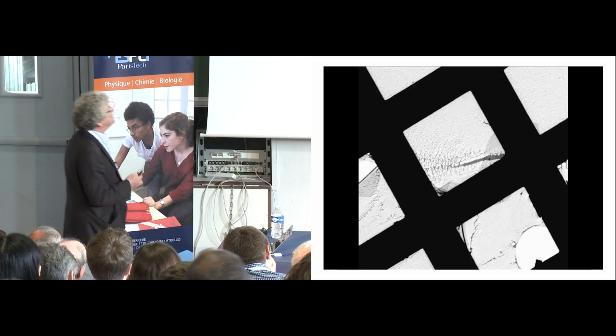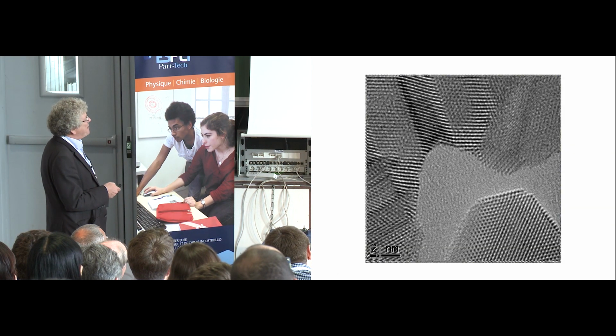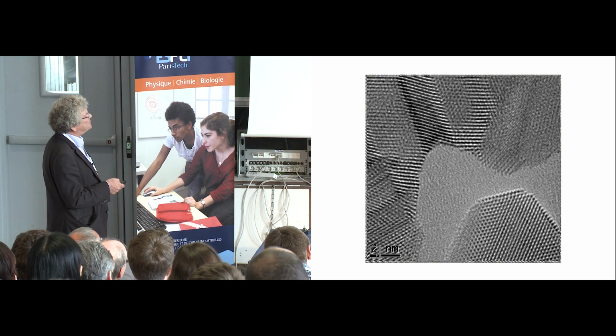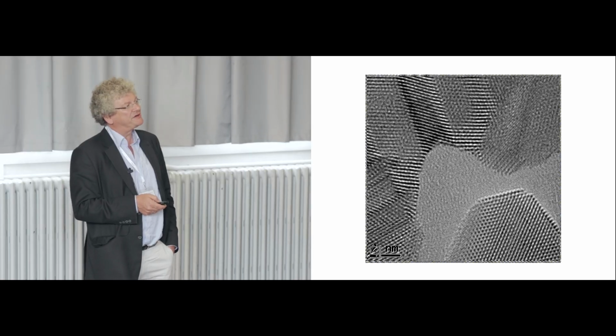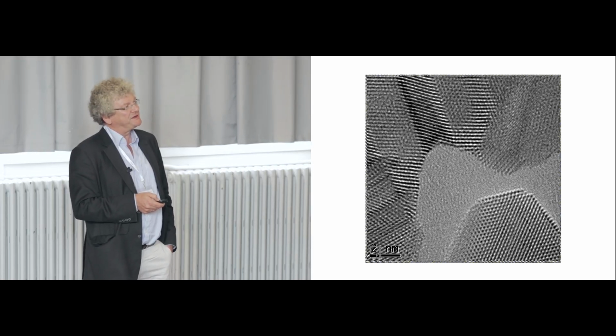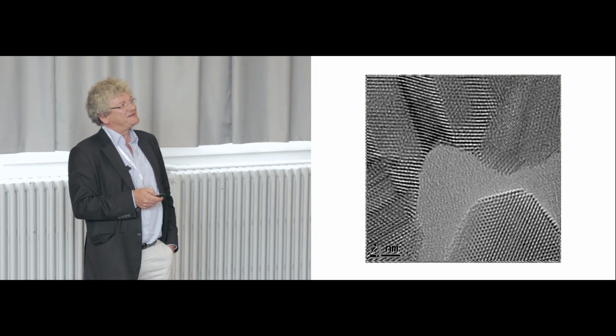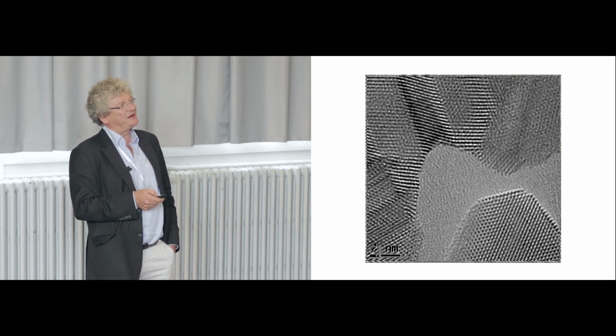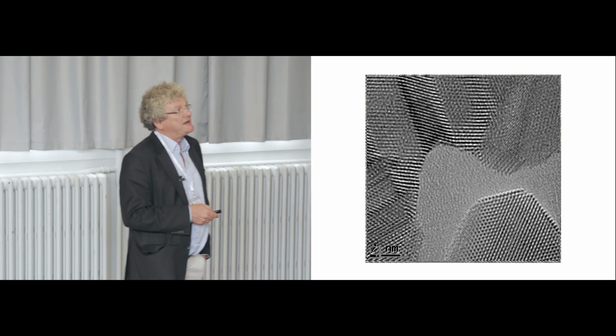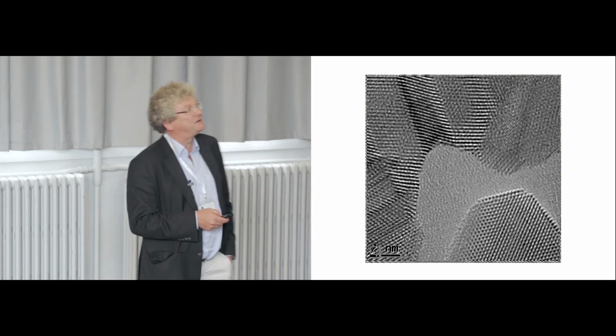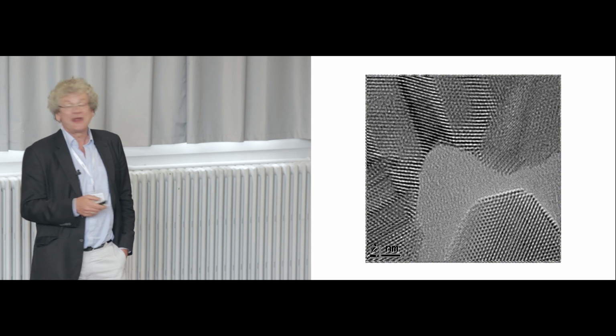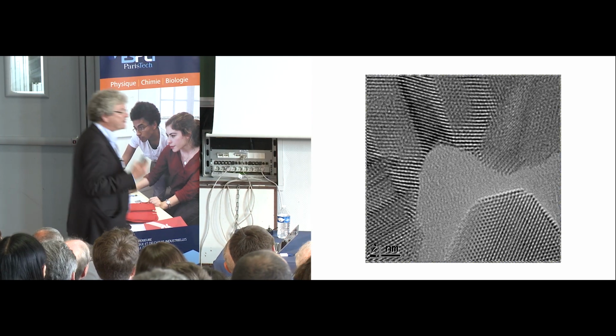And even something like dynamics, here is the fusion of gold clusters on a TEM grid initiated by heat. So you see this cluster coming here, and you can see the atoms hopping from one to the other and how a new surface facet is formed. So very nice things which can be done and which promoted this field in a tremendous way.